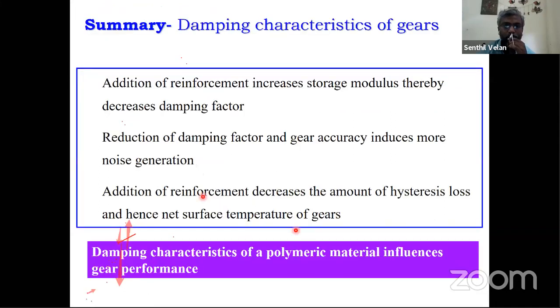So in the damping, we wanted to give some sort of summary out of that. When you add the reinforcement, naturally it will increase the modulus, particularly the storage modulus, thereby the damping factor is reducing. And damping factor reduces and gear accuracy induces more noise generation, and addition of reinforcement decreases the amount of hysteresis and hence the surface temperature. So damping characteristics influence the gear performance. Any machine element is subjected to contact and so on, so the ability to absorb the shocks and vibration, noise and all is also very much crucial. In a way, we were all thinking that okay, when you use a polymer class of material, it will be better. But when you add the fiber, it is getting more complicated. That is what we need to understand from this.